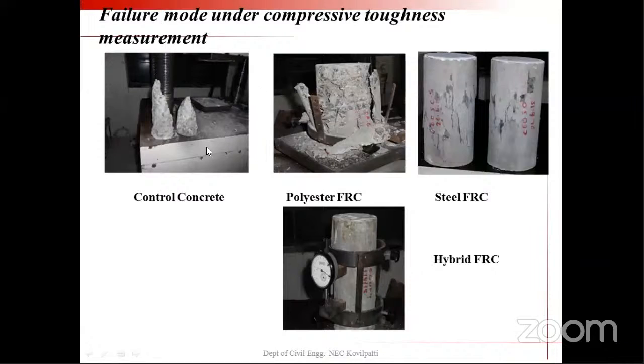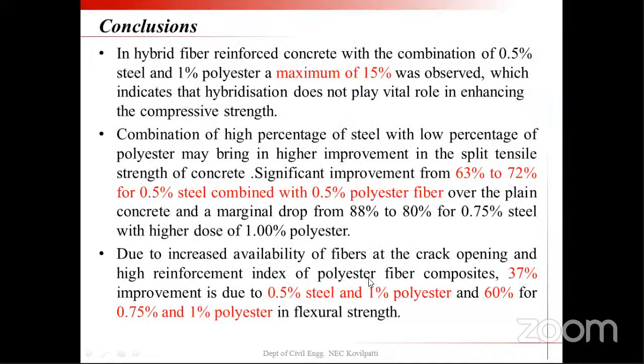So this is control concrete, total failure under uniaxial compression. The polyester fiber series is also poor in withstanding the compressive load, as I already mentioned. And this is a steel FRC series. You can see fewer cracks on the surface. So the multiple cracking localization is a very favorable aspect of this FRC and hybrid FRC, because many fibers will bridge across these cracks and improve the tensile strength, even though the cracked matrix will undergo a large amount of deformation till the complete failure has occurred. And you can see the tested specimen. It is actually a tested specimen, but not much failure cracking has been observed. So it has a very good crack arresting mechanism.